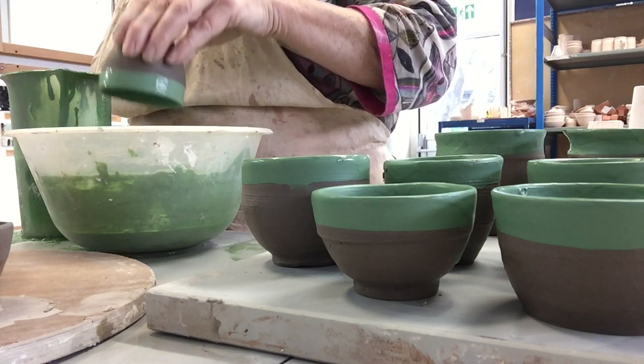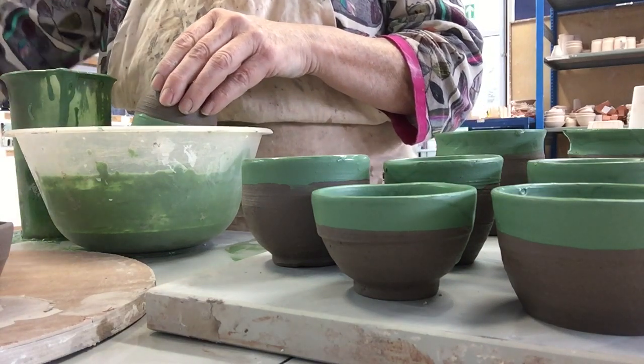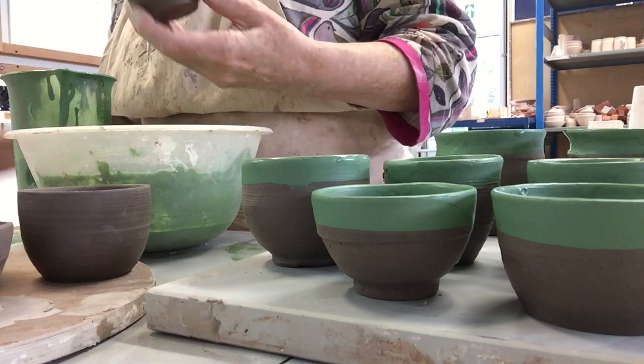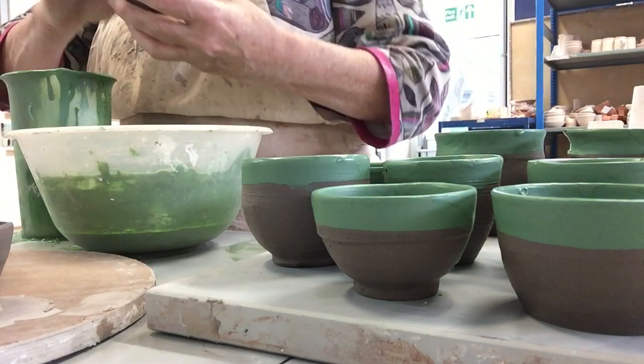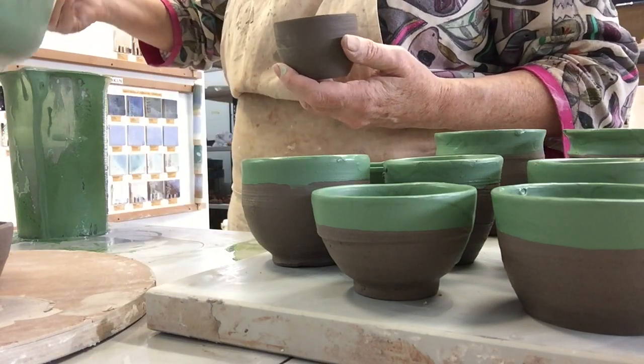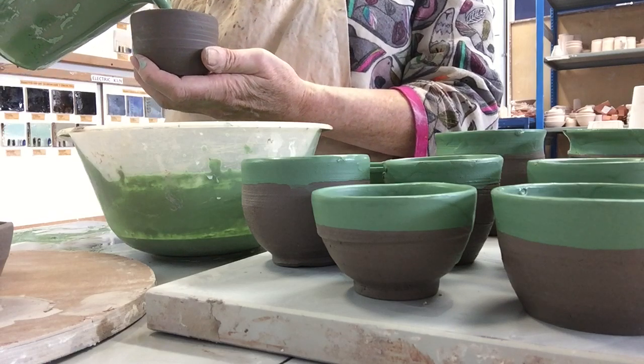Although the turquoise never is apparent in this at all. You've got to be quite careful when you're dipping things before they've been fired, because they could still break, and as the watery slip goes onto the dry pot, the whole thing could disintegrate. So you have to get them to just the right stage.